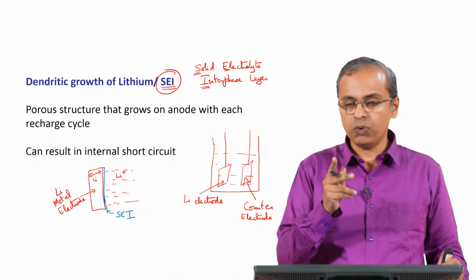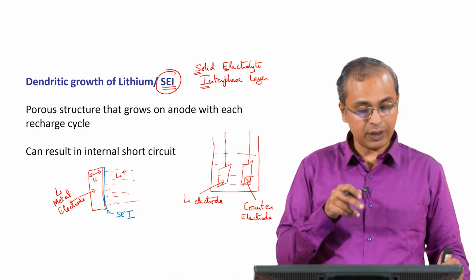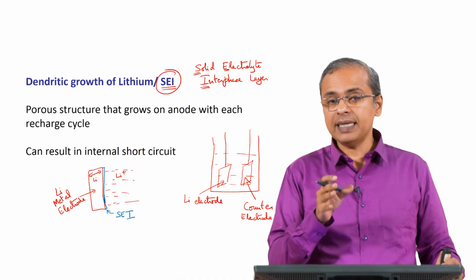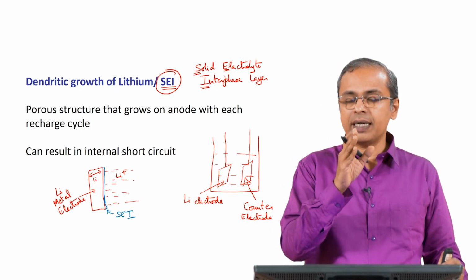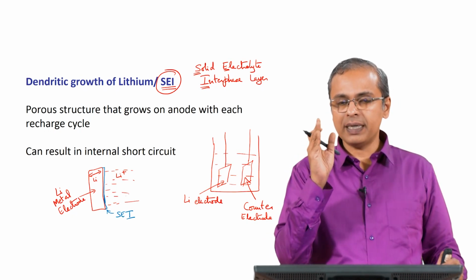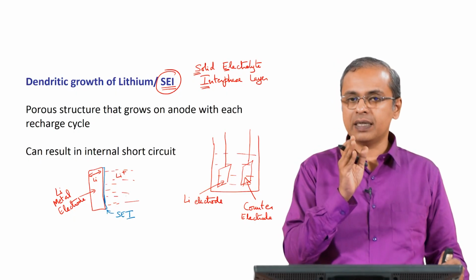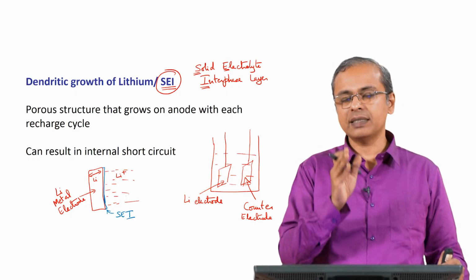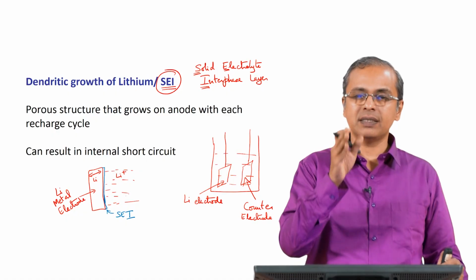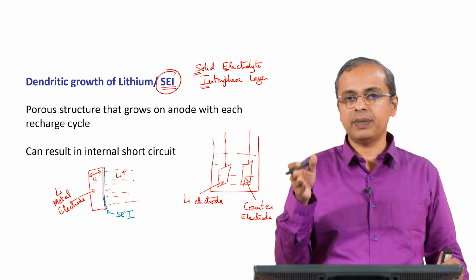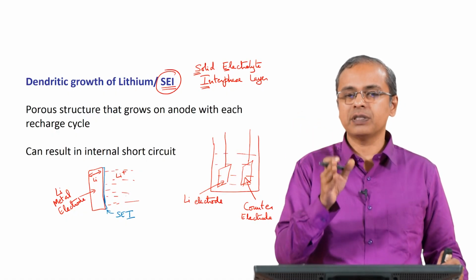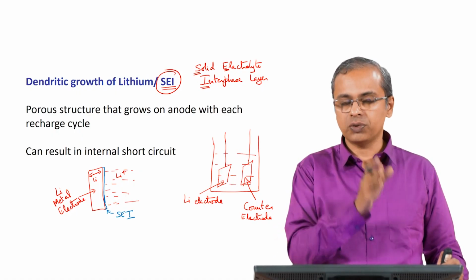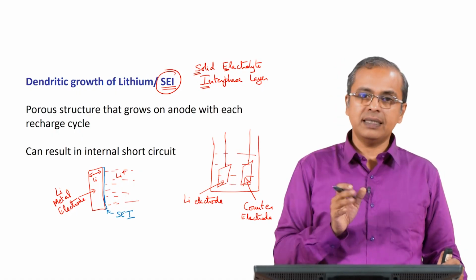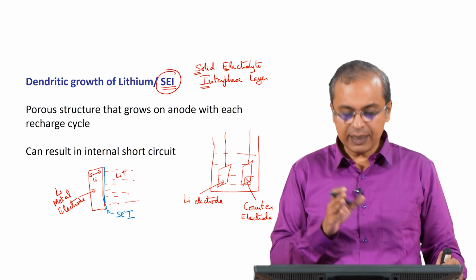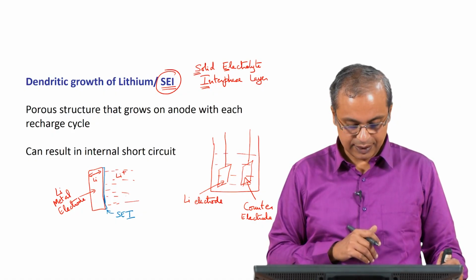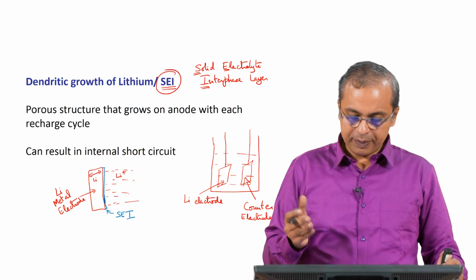The negative is actually two parts. One is that you are adding impedance to the cell, and the second thing is you are irreversibly consuming a little bit of the electrolyte as well as a little bit of the electrode. So, this SEI layer is essentially a wasted surface layer because it has used up a little bit of the electrolyte, irreversibly changing the electrolyte in some way, and it has also used up a little bit of the metal. So, in that sense it is also not a very positive thing, but it protects the electrode, so that is fine. But there is another problem here. So, there is the SEI.